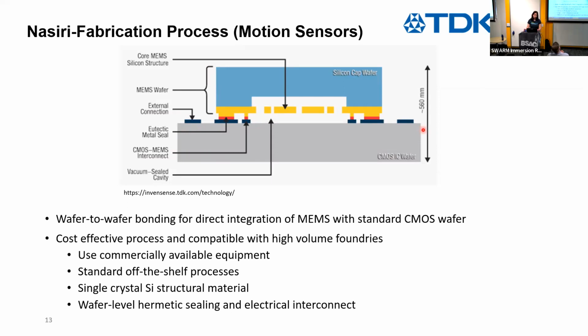This process is very cost effective and is compatible with high volume foundries. All the process steps use commercially available equipment, and all the processes are standard off the shelf. The structure layer uses single crystal silicon. That is very nice for the designer to work with compared to polysilicon, because single crystal silicon has better material properties than polycrystalline silicon. At the end, we do a wafer level eutectic bonding of the MEMS wafer to the CMOS wafer. This creates a hermetic seal, and we also have an electrical connection between the CMOS and the MEMS.